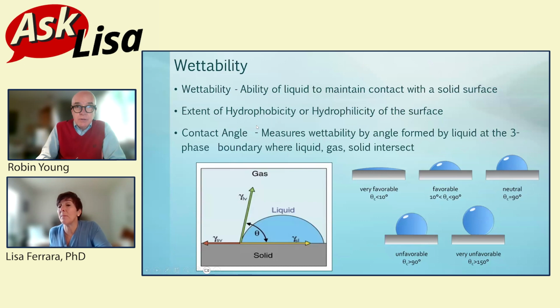It'll take me back to how are you going to measure it first? Wettability is the test. It's very common. It's very easy for the most part. You're just looking at that contact angle of a drop of liquid, a drop of water, on that surface. And we've looked at it for PEEK surfaces and titanium surfaces of different roughnesses. And you really want to be between a 10 and 90-degree angle here. This is the perfect contact angle you would want to see for good cellular adhesion, optimal surface energy, basically.